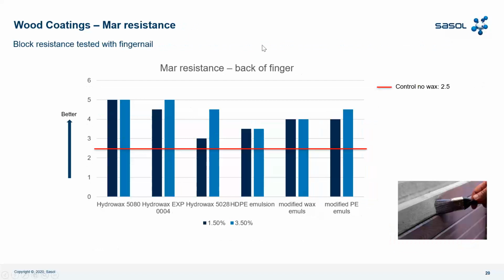Then I go on to show you the mar resistance, or burnish. We have here a block resistance test with fingernail. You need to read the test so that the highest value means better. So we have Hydrowax 5080, the 88 melting emulsion, that achieves the best results of the test at 1.5%. Then follow Hydrowax experimental 004 and Hydrowax 5028. Hydrowax 5080 achieved the best results with respect to the other emulsions, and also the competition.